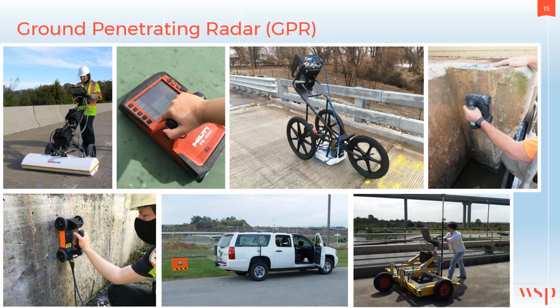One of the things to keep in mind with ground penetrating radar is that the depth of penetration of the signal and reflection is a function of the frequency of the signal. Lower frequencies tend to have deeper penetration, higher frequencies less so. But the wavelength associated with those frequencies means that the low frequency signals do not give as much precision in the response, or accuracy. So there is a trade-off between depth of penetration and the precision of the features that you can detect.